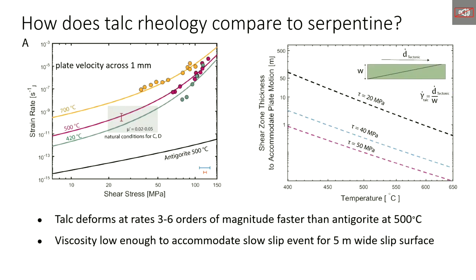So let's compare talc to serpentine. Talc, at say 50 megapascals and 500 degrees, you're talking effective viscosities that are orders of magnitude lower than serpentine. So where it is present, it could really, really be important.